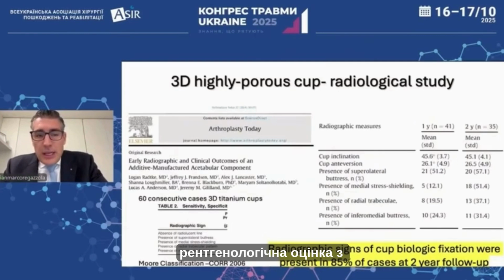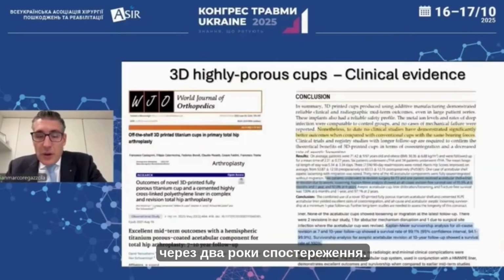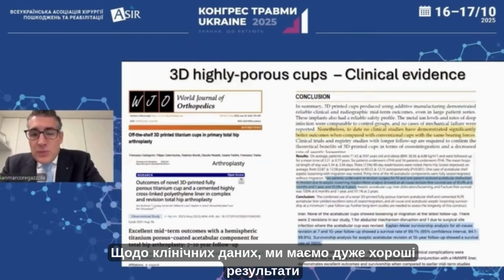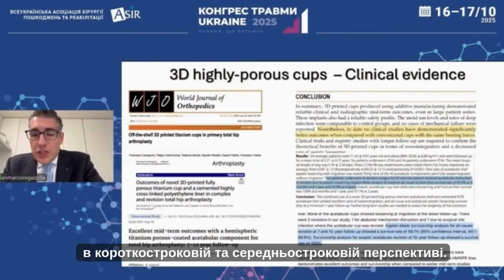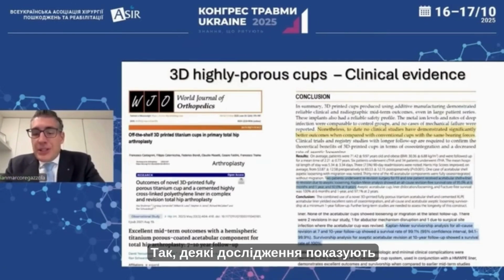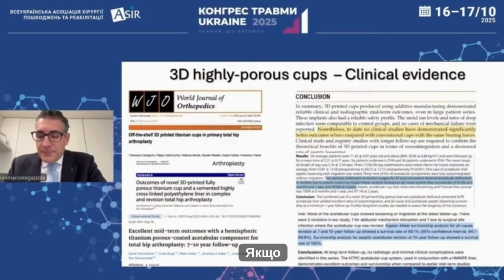Also, early radiological evaluation with Moore classification showed, in these 60 consecutive cases, better results and integration of the component up to 85% at 2 years follow-up. Regarding clinical evidence, we have very good results at short and mid-term, up to 10 years. Some studies show up to 100% survival rate, so no aseptic loosening.